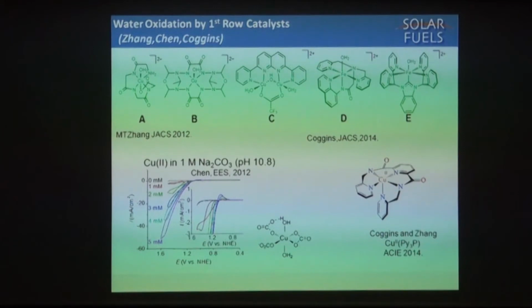And the first thing that happens is the complex decomposes to an oxide. So this is actually done in non-aqueous solvents with added water. Here's a recent copper-2 case, which is important because the reactivity of that complex is comparable to cobalt. So we're spending a lot of time looking at copper-2 chemistry.